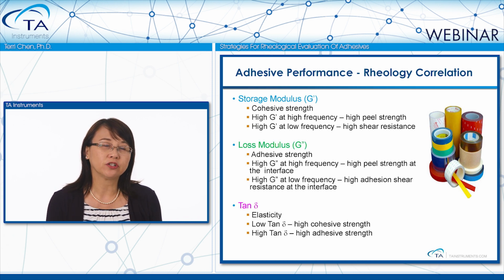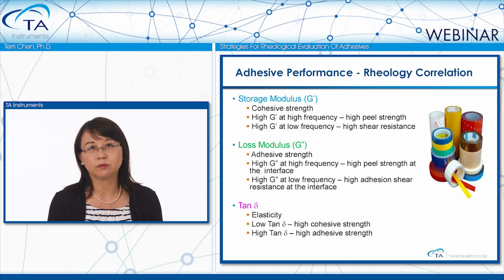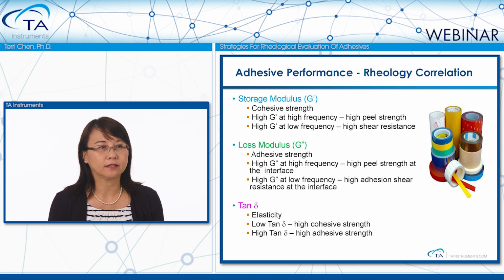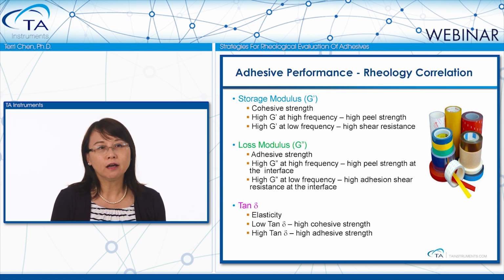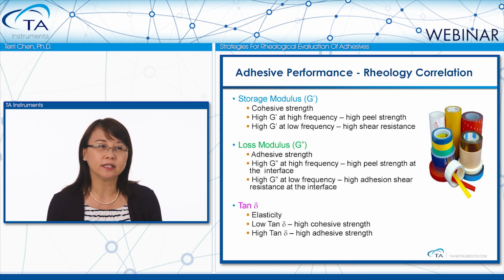The loss modulus, G double prime, describes the viscous response of the material. So it correlates to the adhesive property at the interface. A high G double prime at high frequency correlates to high adhesive peel strength at the interface. A high G double prime at low frequency correlates to a high adhesive shear resistance.